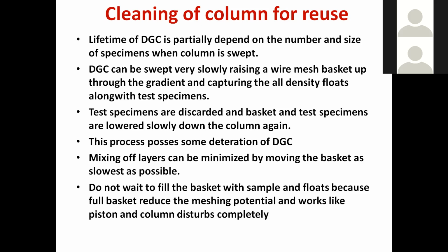Why are we using this slow speed? Because your column is so delicate. Liquids are there and liquid layers are there. If you do it fast, these layers will be disturbed and your column will also be disturbed.